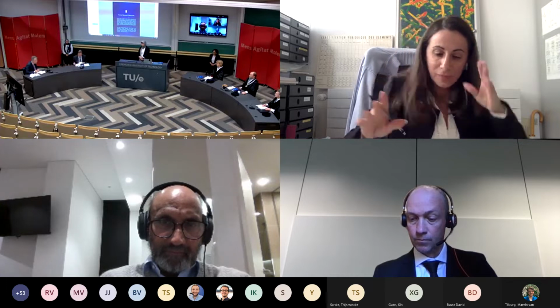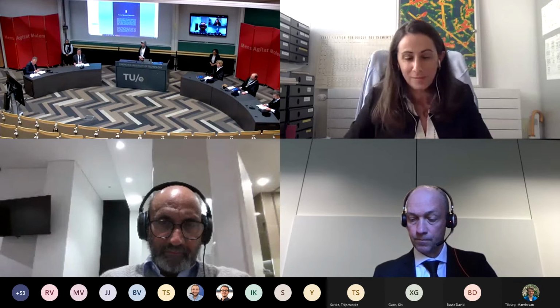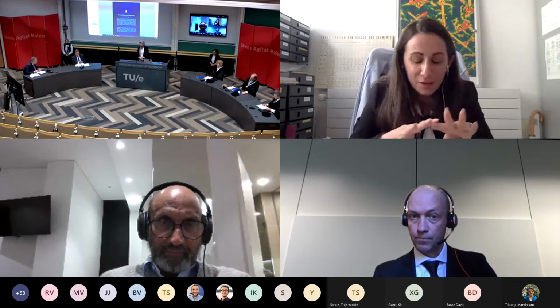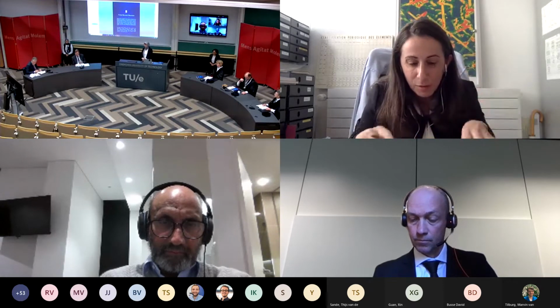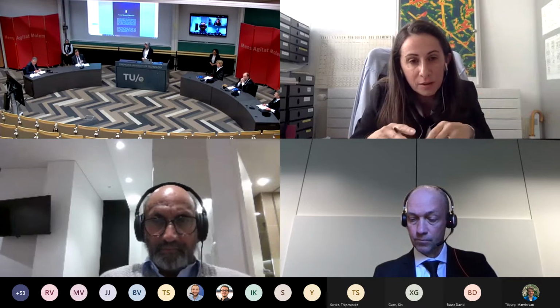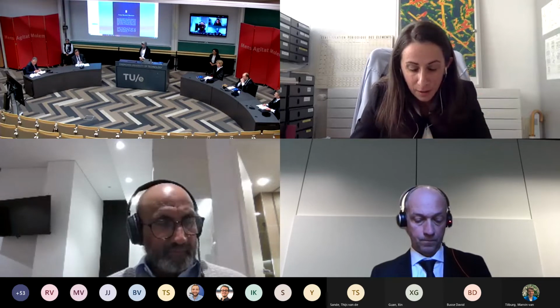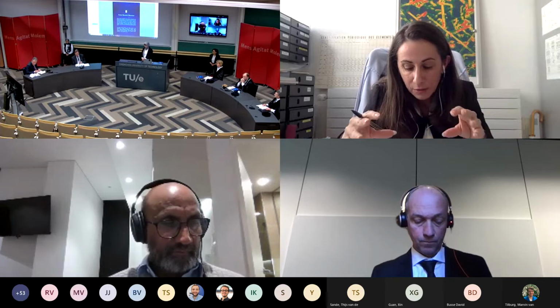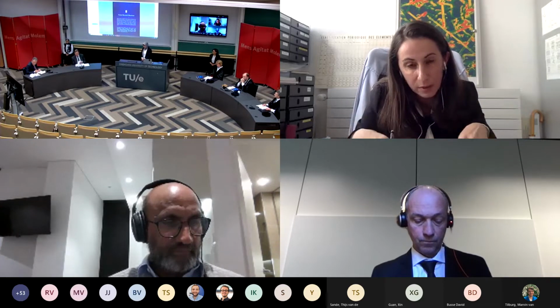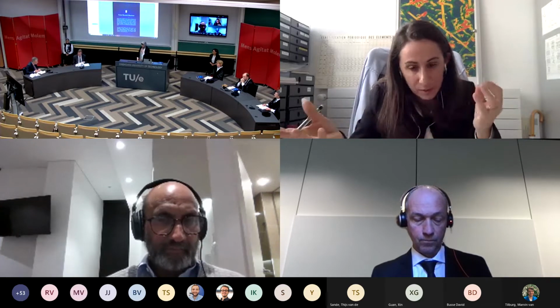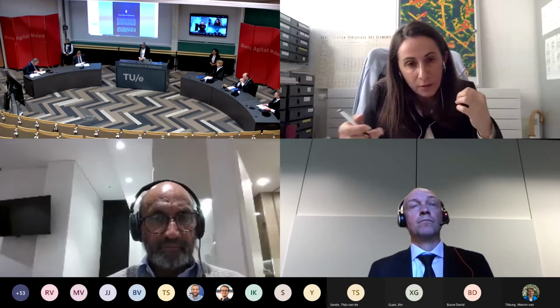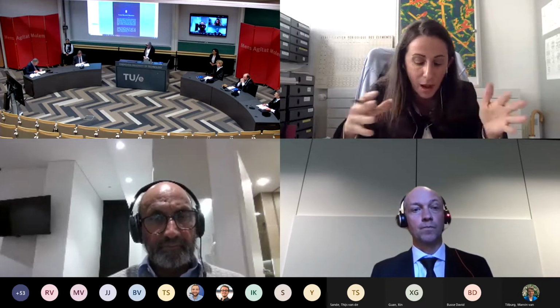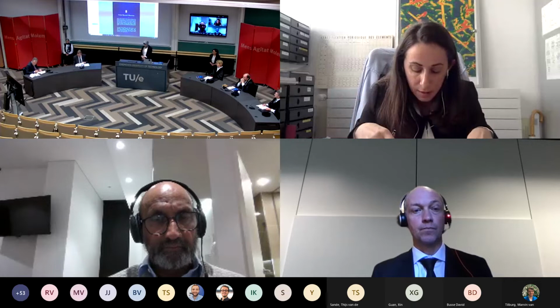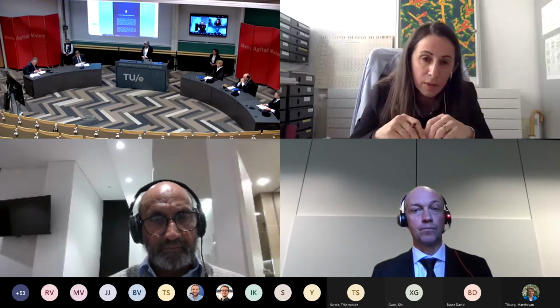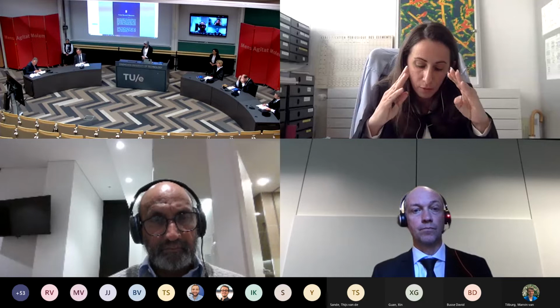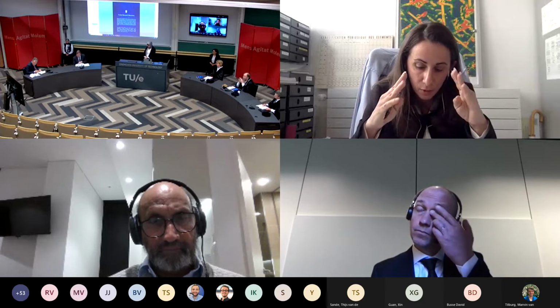Okay, and I have just a small question before finishing. It's a detailed question. Regarding the growth of gallium arsenide nanowires, you clearly demonstrate that the deficient gallium content in the droplet causes stacking faults or polytypism, because the effective V/III ratio is likely increased. This gallium deficiency is consistent with the tapering of the nanowires that you have observed.